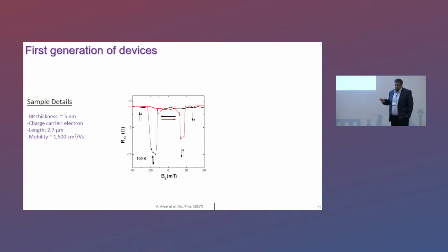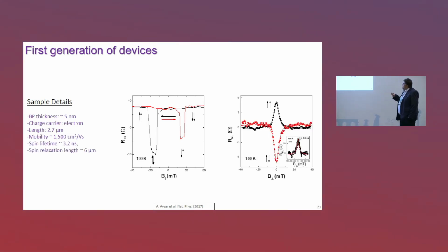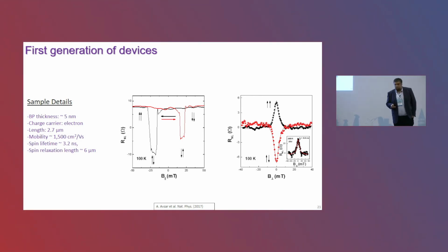Basically, the sample had a mobility of around 1,500, and we were seeing very clear spin transport in this material, as well as spin precession measurements, and we could extract some important spin transport parameters. For example, the spin lifetimes in this material appear to be around 3 nanoseconds, with the relaxation length exceeding 6 micron. So this is one of the first demonstrations of spin transport in a semiconducting material, and it's only the second material which shows spin transport in the two-dimensional limit.